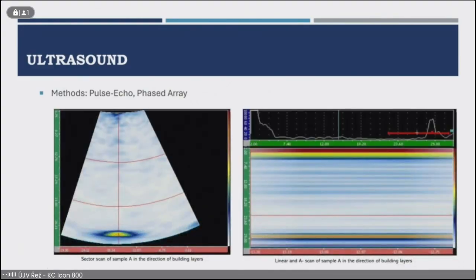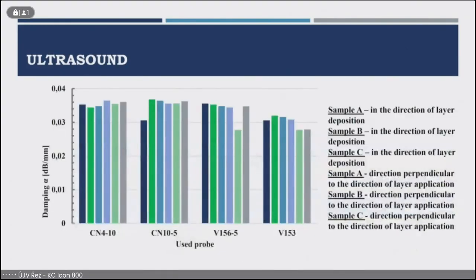Here you can see a sector scan of sample A, a linear scan, and also a scan of sample A in the direction of the layer deposition. Also with this method, attenuation for individual probes was monitored. Here you can see the attenuation for each sample, in each direction, and for all probes.